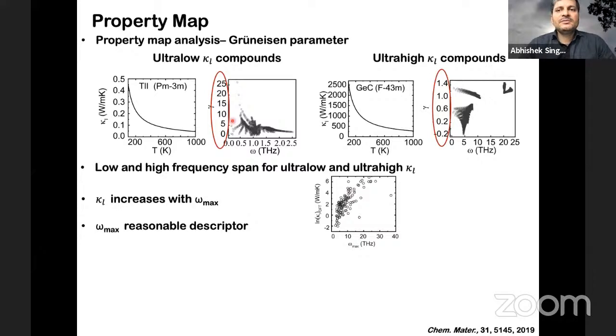Next, the Gruneisen parameter is the only one which is calculated within the quasi-harmonic approximation. It's not something which captures anharmonicity directly, but for thermal conductivity, you need to know how anharmonic your crystal is. And we can get some information by looking into the Gruneisen parameter. So this is what we did. And here again, we found that if the spread of the Gruneisen parameter is very high, thermal conductivity is low. If the spread is low, thermal conductivity is high, so it's an inverse relationship.